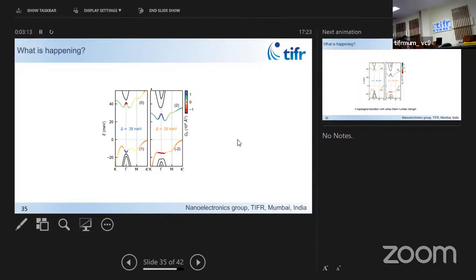And my contention is that almost all devices that people measure across the world have some bit of strain in the moiré, because it's impossible to get over a micron square or 2 micron square a uniform crystal. This is strain in the twist angle. Yes, it's twist angle disorder, not the disorder of other kind.